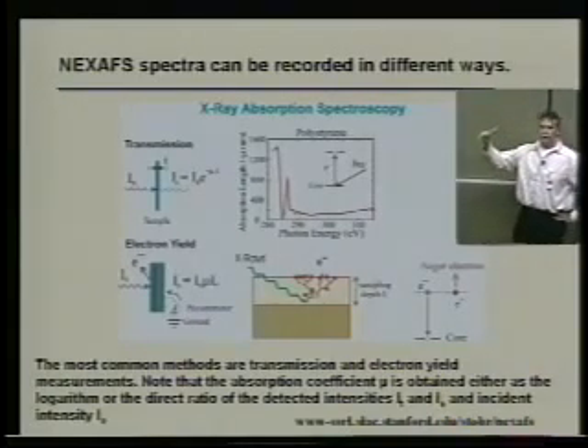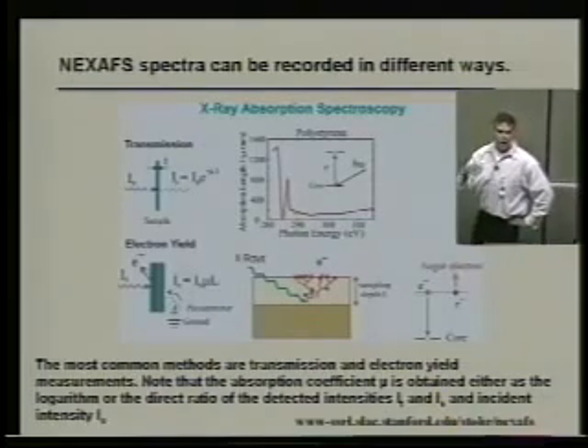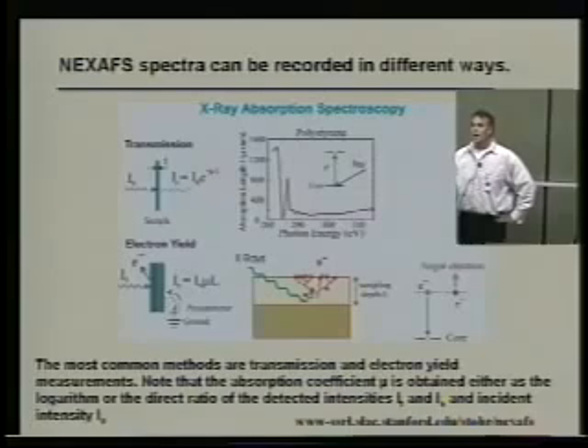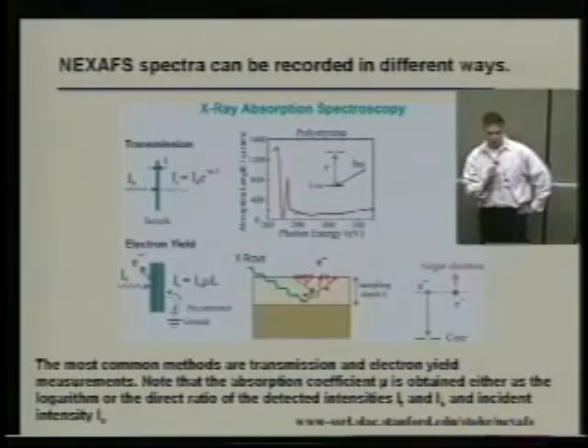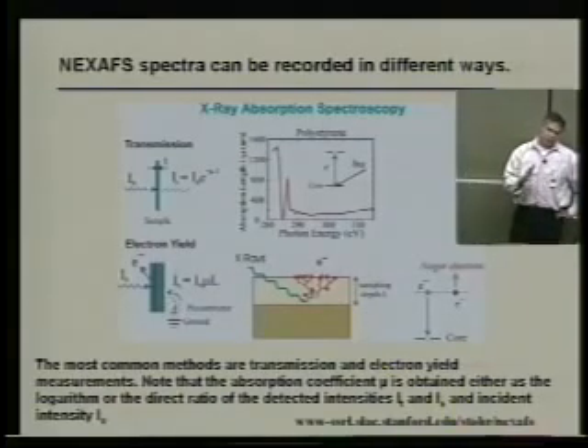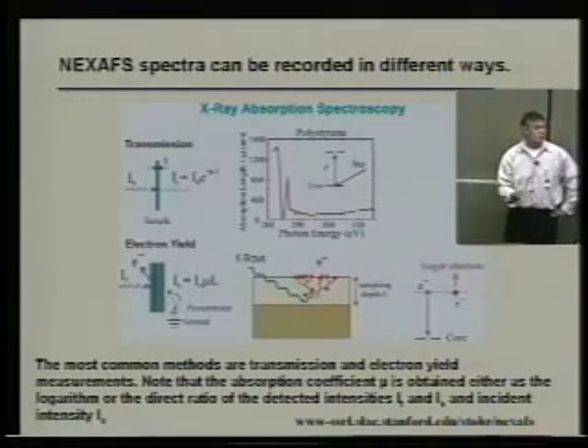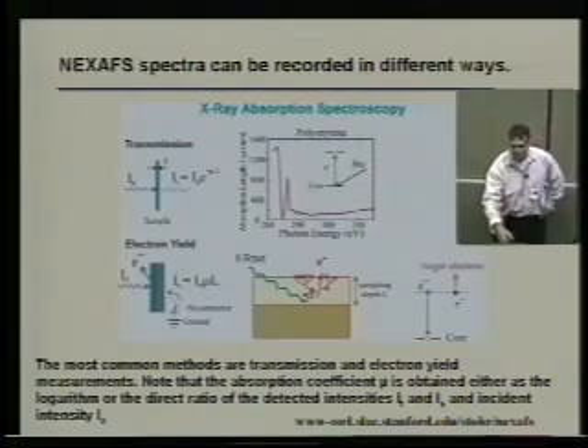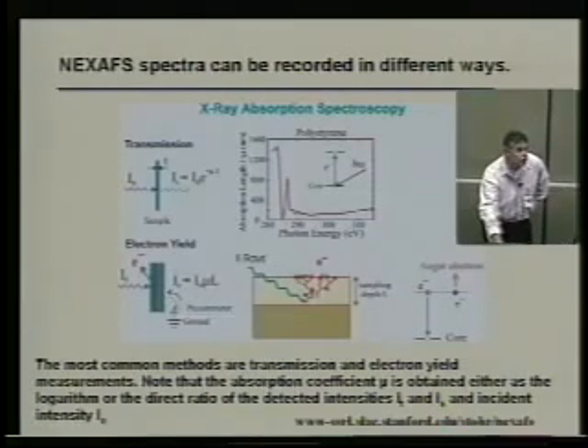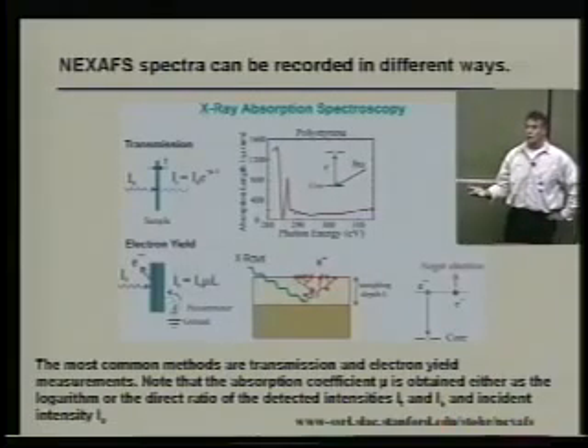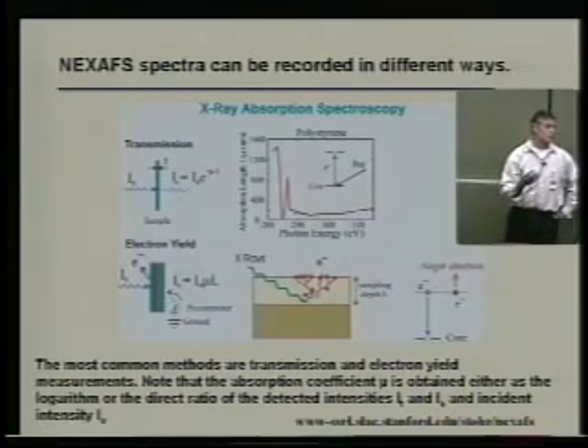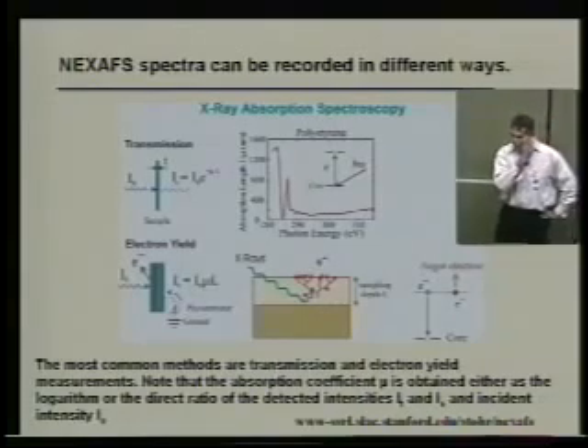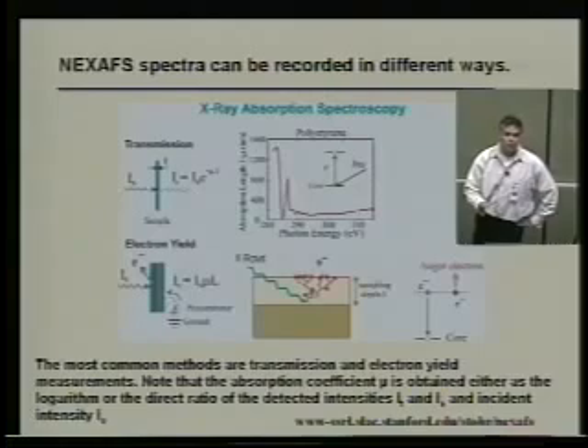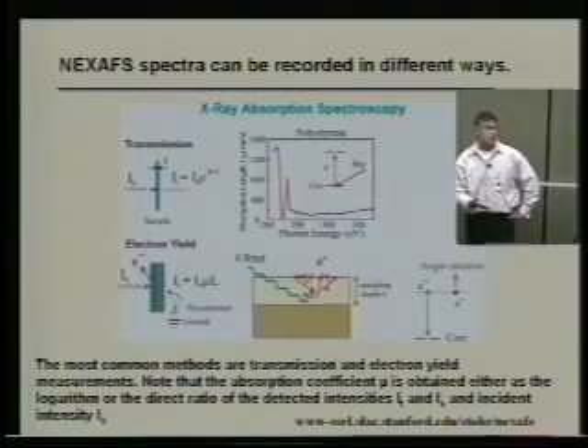And all you have to do is have an electron counter, a channeltron, or a channel plate, and you can count the number of electrons that are coming off, and that's proportional to the original core hole. So it's proportional to the absorption coefficient. The nice thing here is it's a fairly simple measurement, because either you're counting electrons, or even simpler, you just attach a wire to your sample, and you measure the drain current coming off your sample, and you can measure electron yield. It's a very simple setup. I like it because you can now tune your samples to be quite surface sensitive because you're dealing with electrons rather than photons.